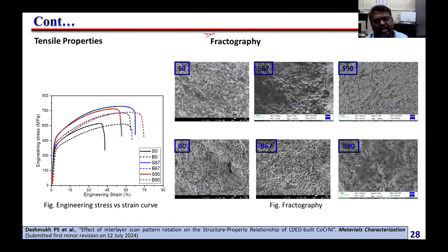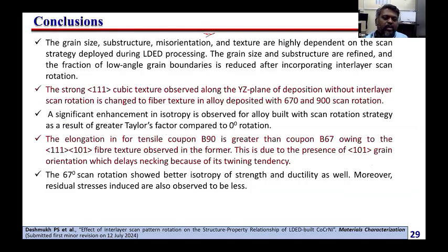In all cases it is showing dimples. The dimple fracture structure basically indicates that it is an FCC. Usually ductile samples will fail through these dimples. You will observe the dimple structure in ductile fracture. Okay, so that's what we understood. So by using these different scan strategies, what we understood is we were able to control the microstructure and texture both.